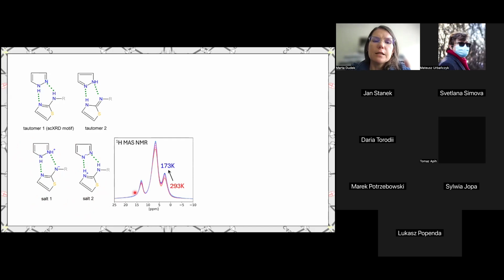So then we run proton MAS experiments under very fast magic angle spinning at low temperature, or actually in the whole temperature range up to 173 K. And we did not see any signal moving. So this could happen if we were to have this proton transfer. So at lower temperatures, we should see some additional signals appearing.